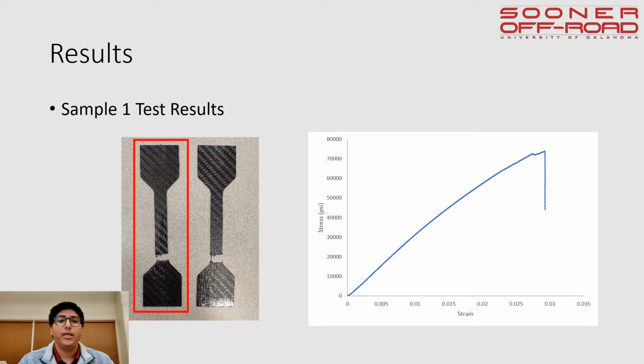As mentioned previously, the carbon fiber samples were tested to confirm their strength was equal to or greater than that of 4130 steel. In this sample, shown on the left, we see that the failure was within the sample area, which is necessary for consistent data. From the graph, we can see that the yield strength was 72,500 psi, with an ultimate tensile strength of 73,800 psi.